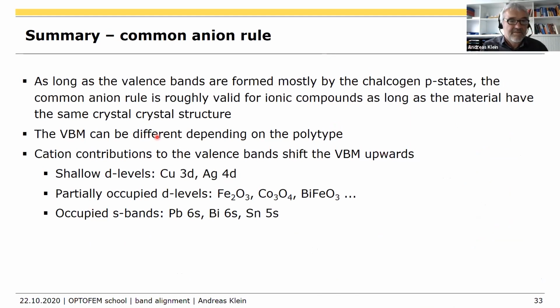Okay, so the common anion rule seems to be valid as long as the valence bands are formed mostly by the chalcogen p states. But we still have to take care about the different polytypes. Cation contributions to the valence band shift the valence band maximum upwards, and the candidates for that are especially copper and silver d orbitals, and partially occupied d shells, so that means iron oxide, cobalt oxide.